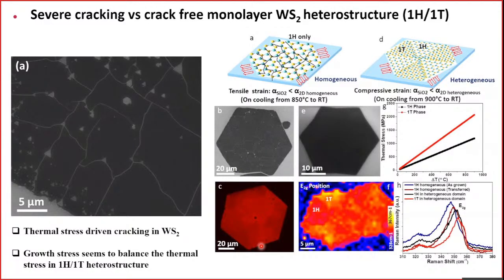When we are talking about defects, a lot of point defects, as I also mentioned earlier, we can also introduce voids, which act as an enhancement in the emission. But the question is how mechanically reliable the structures are that we can produce when we keep increasing the defect concentration. So this is one extreme case. When we introduce more and more defects, we have lots of these voids. In addition to these voids, you can also see almost a spider net.